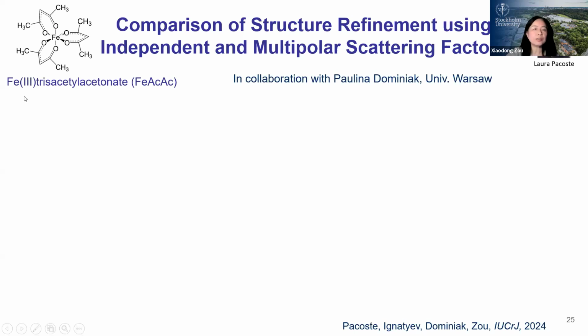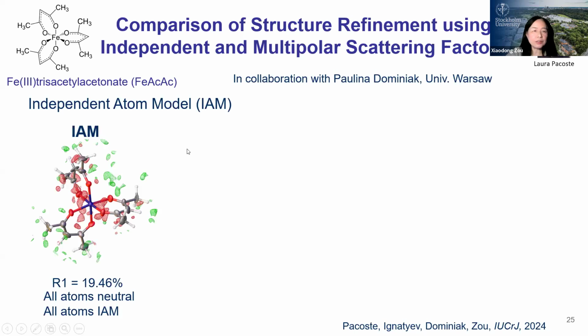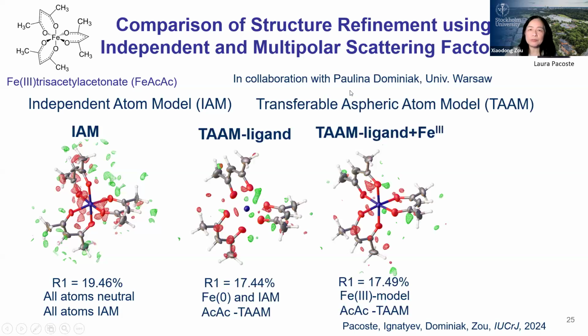This is the molecule. This is the independent atomic model, as you see here. And we do see a lot of negative and positive densities here. This is where we used all atoms neutral, the independent atomic model. But in collaboration with Paulina Dominiak's group at the University of Warsaw, we applied this transferable aspheric atom model. It's called the TAAM model. Basically, it's a multipolar scattering model. It assumes that atoms in the same chemical environment will have similar atomic scattering factors, but different chemical environments will have different scattering factors.